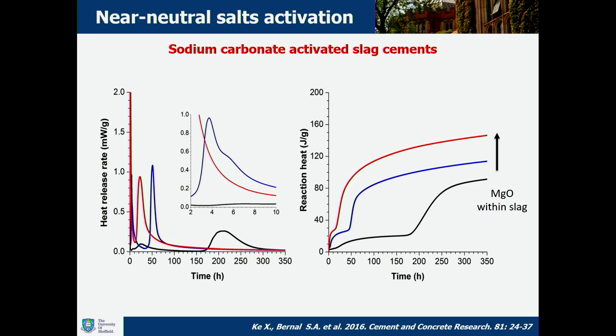So here I'm showing some isothermal calorimetry results again, where we can see that if we use slags with different chemical compositions, first, we see that the precipitation of reaction products is taking place at different times. And also we can see here how when the magnesium content within the slag increases, we can also achieve higher degrees of reaction.